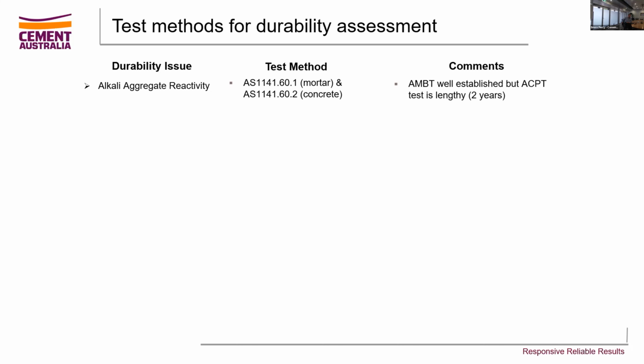The accelerated mortar bar test is well established, as we all know. It can be carried out by numerous NATA accredited laboratories around the country. But the downside really is that this is an accelerated test. The concrete prism test is also an accelerated test, but it takes a lot longer to run to completion. I put there 2 years, but certainly within the first 18 months or so you'll know whether you're going to be on track for a successful result.